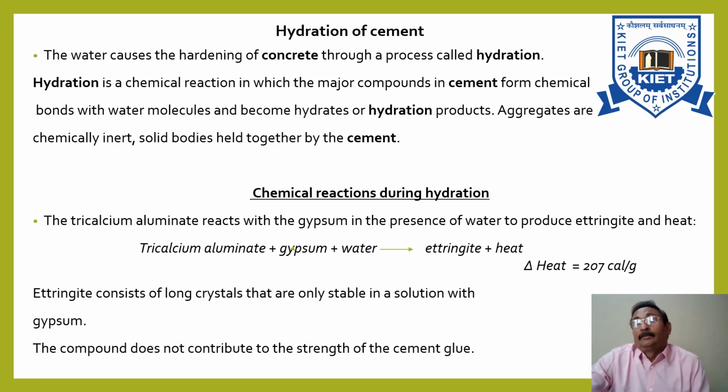It is also possible that both mechanisms, through solution and solid state, may occur during the course of reaction between cement and water. The former mechanism may predominate in early stages since a large quantity of water is available, and the second mechanism may dominate in later stages of hydration.